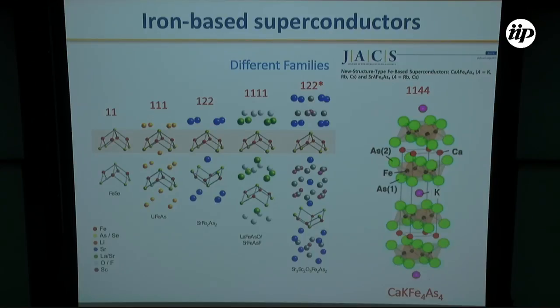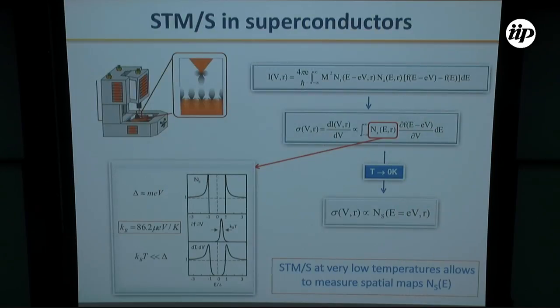So here I will present new data in a recently discovered stoichiometric superconductor, calcium potassium iron 4 arsenic 4, which has a critical temperature of 35 Kelvin, the highest critical temperature among the stoichiometric compounds. It was first synthesized last year, first in polycrystalline form, and a few months later in single crystal form by the group of Paul Canfield.